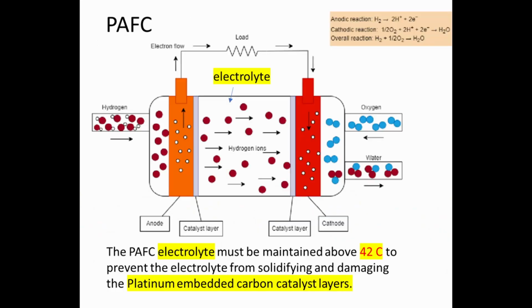As phosphoric acid is solid up to 42 degrees Celsius, the PAFC must be warmed to this temperature, greater than 42 degrees Celsius, for its electrolyte to melt and begin producing electricity. The PAFC must be maintained at a temperature above 42 degrees Celsius to prevent the phosphoric acid from solidifying and damaging the platinum-embedded carbon catalyst layers on either side of the electrolyte matrix.